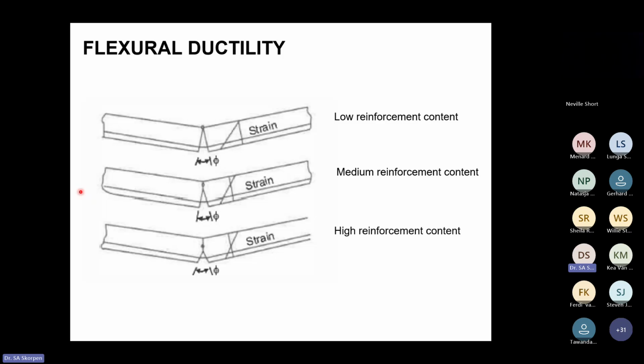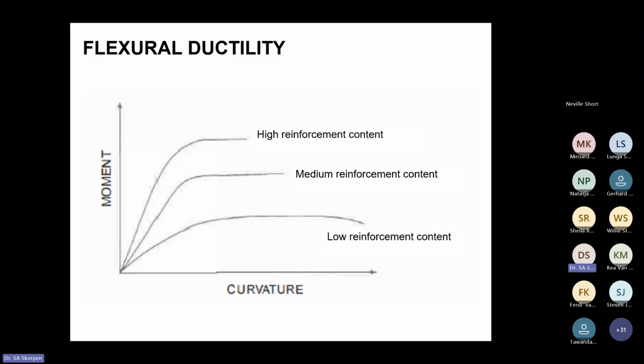So that drop in the neutral axis leads to an increase in strain in the concrete, and that results in a loss in ductility. And you can just see that here with these plots of moment versus curvature for low, medium, and high reinforcement contents. You can see the more curvature you can handle in the cross section, the more ductile the failure mode is going to be. So that's just showing as you increase the amount of reinforcement, yes, you do increase the moment it can carry, but you decrease the ductility.